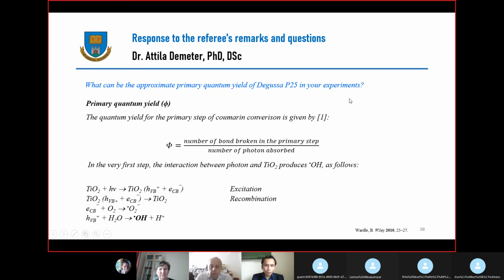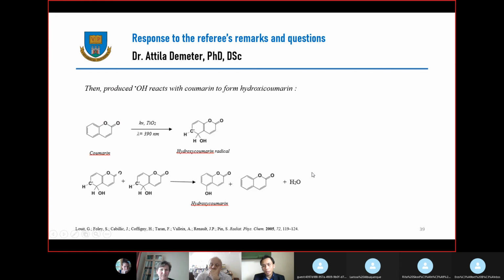And regarding the specific question, we try to calculate the quantum yield, in this case for Degussa P25, under UV illumination. The primary quantum yield we can calculate with this equation, and in this case, in the first step of the reaction, the reaction of the photon in the titanium dioxide produces the hydroxyl radical, and then this hydroxyl radical attacks the coumarin.